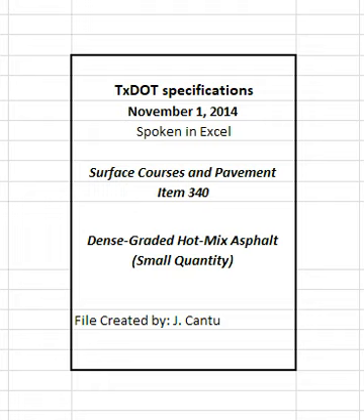Trim the cores immediately after obtaining the cores from the roadway in accordance with Tex-207-F if the core heights meet the minimum untrimmed value listed in Table 12. Trim the cores on site in the presence of the engineer. Use a permanent marker or paint pen to record the date and lot number on each core as well as the designation as Core A or B.